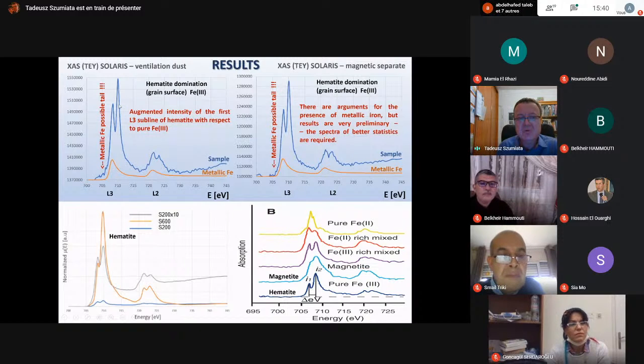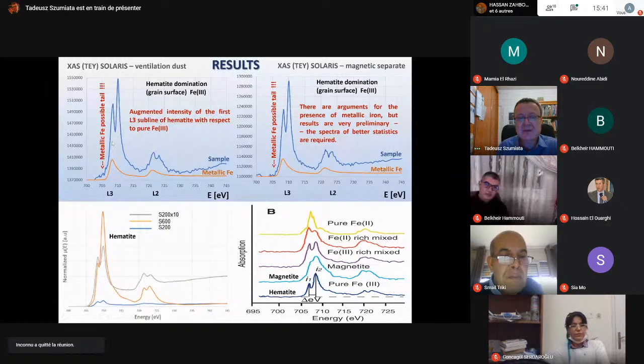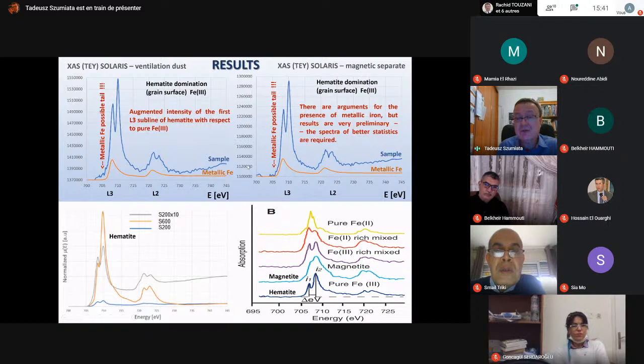Here in blue you can see experimental curves. They are not the curves of absorption. The method is of course based on absorption, but the detection is based on the measurements on the current of emitted electrons, so it looks like emission. And this method is sensitive to the fine structure, not only to the presence of a given element, but also to the environment, the chemical environment.